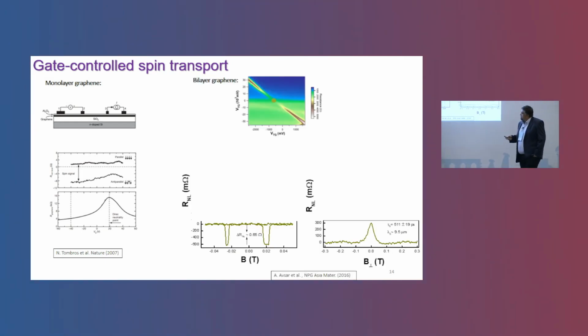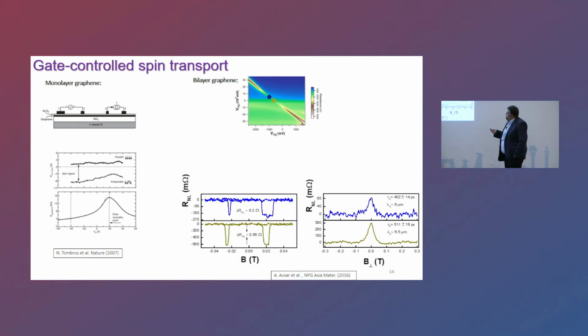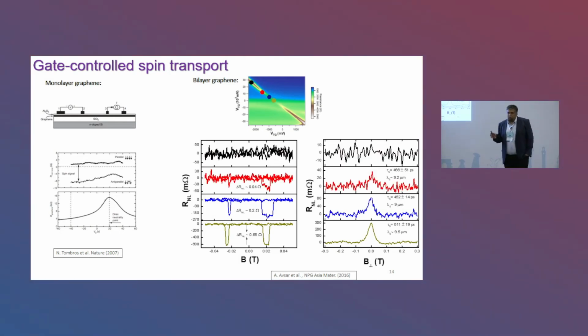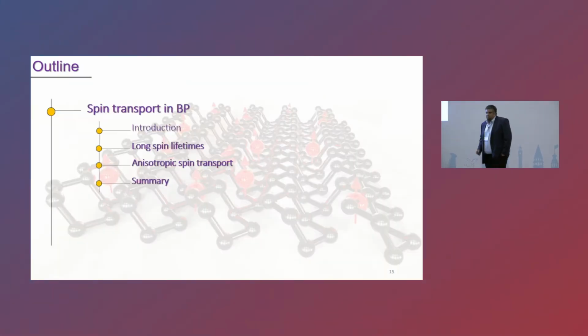So we tried to solve this problem by using bilayer graphene. In bilayer graphene, whenever you apply a vertical electric field, you can induce a band gap, and we have shown that as you open the band gap, you can also control the spin propagation within the material. But there are still lots of issues, as it only works at very low temperatures. So what we were looking for was a two-dimensional material which has a sizable band gap and which can also host spin transport very well. That's how we started with black phosphorus.